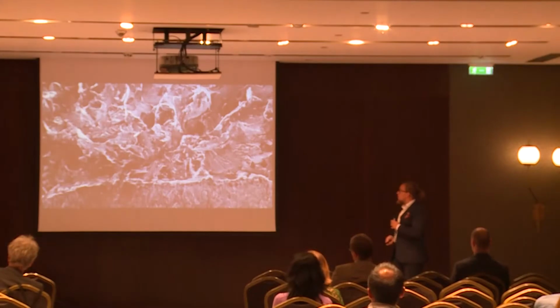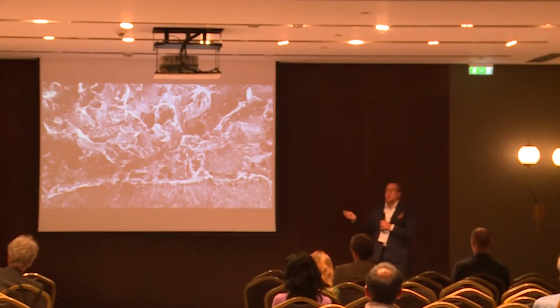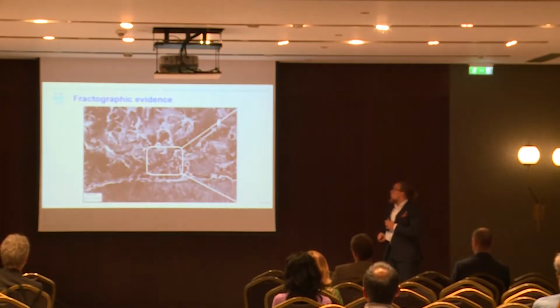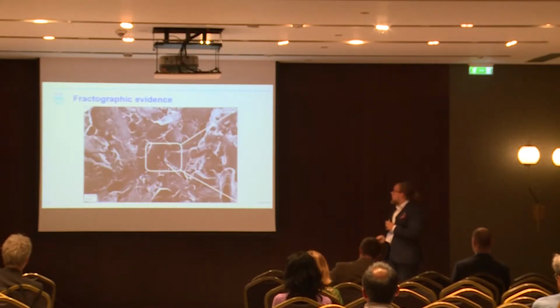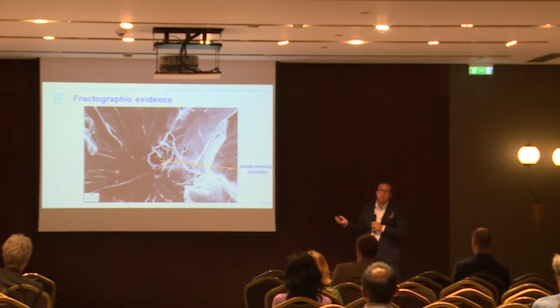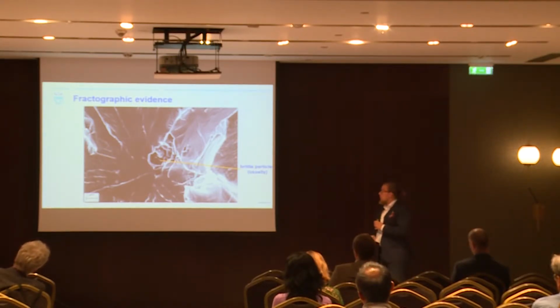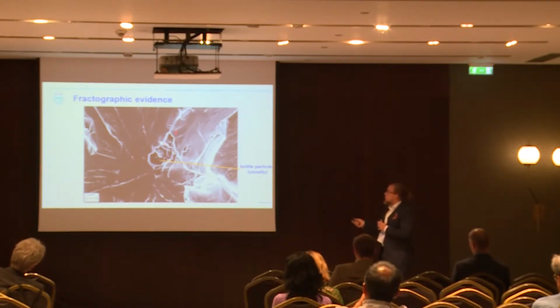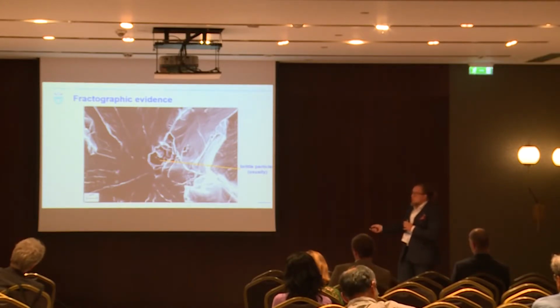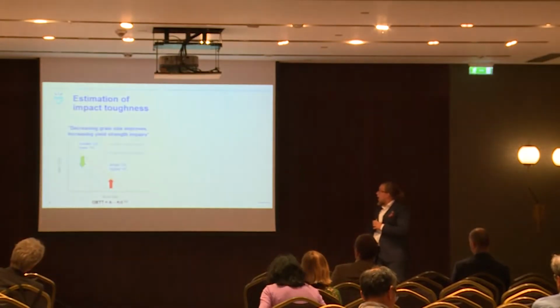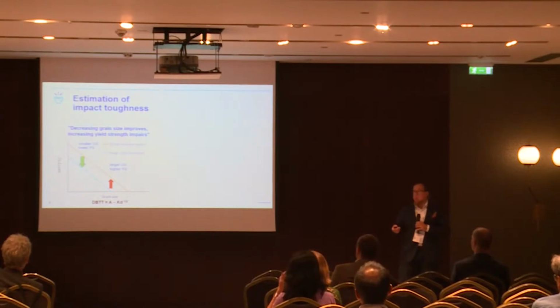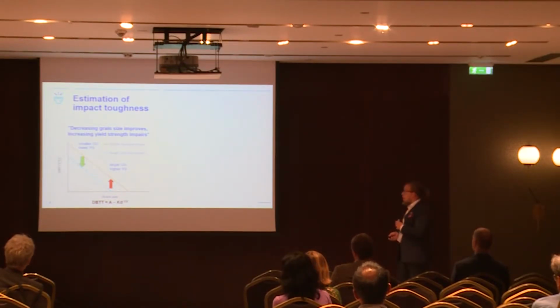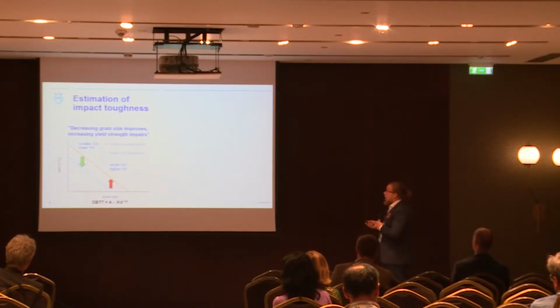To start with empirical findings, here we have a very generic fracture surface, and when we zoom in deeper into the material, we usually find a generic brittle particle that has nucleated the primary failure of the material. We see that the grain size that surrounds this particle can also play a significant role. Many studies have been dedicated to the estimation of impact toughness transition temperatures, and the key idea behind all this is that decreasing grain size improves, and increasing yield strength impairs, the toughness properties.